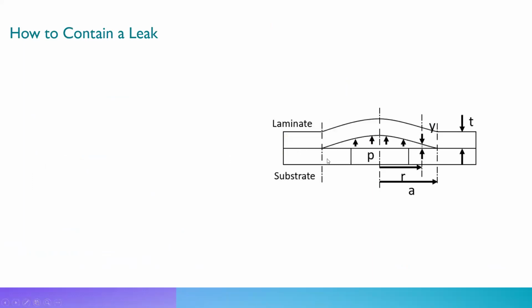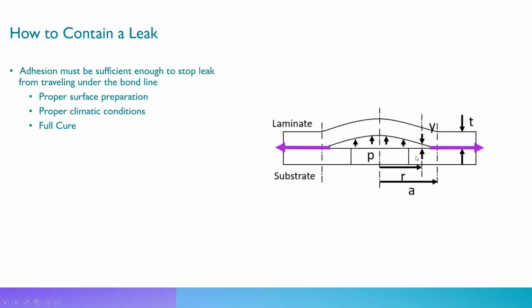Let's say we have a substrate here, we have a hole that you're looking at here, and the outer top part is our repair laminate. So the first thing we have to ensure is that our adhesion is strong enough so that the leak just doesn't come out the edges of the repair.